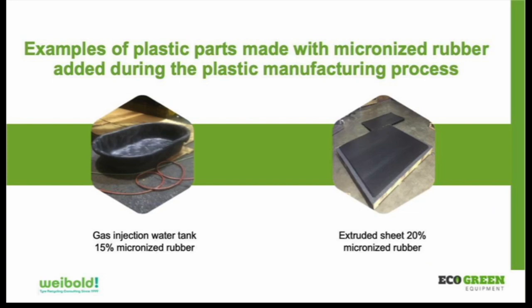So, what are some examples of parts that are made with micronized rubber that is added during the process? Not a pre-pellet, but it can be mixed right in. Well, here's a couple parts that I worked with. The one on the left is from a gas injection company. These were water tanks used for cattle feeding or cattle watering, small goats, pigs, cattle, etc. And in this process, they're able to introduce up to 15% micronized rubber, not in pellet form, but just direct rubber.